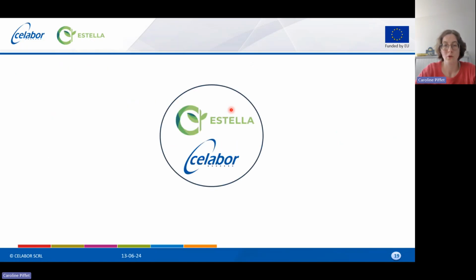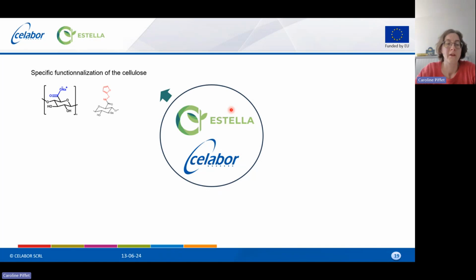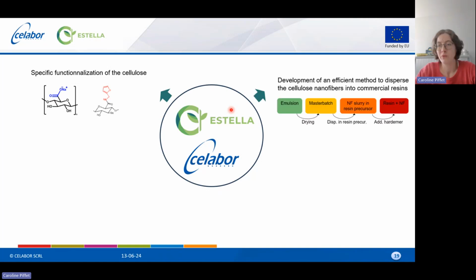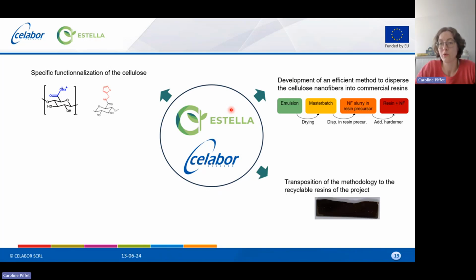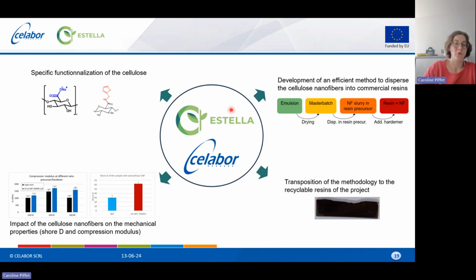And so to conclude, for this ESTELLA and CELABOR results, we achieved to functionalize the cellulose with different functional groups, carboxylate and furfuramine. We developed an efficient method to disperse the cellulose nanofibers into commercial resin, and we transposed this methodology to the recyclable resins of the project, and we showed the impact of the cellulose nanofibers on the mechanical properties, on the Shore D and compression modulus.